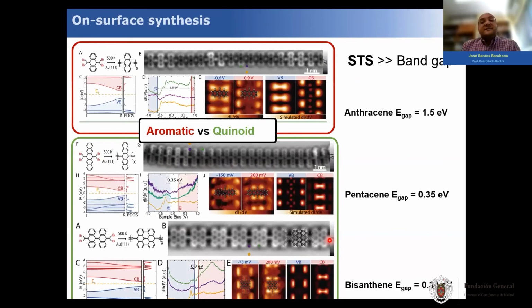Well, by STS, scanning tunneling spectroscopy, we can calculate, we don't calculate, we measure the band gap of the molecules. And for the case of the aromatic anthracene, this band gap is a low band gap of 1.5 electron volts. Whereas in the case of the quinoid structures, like the pentacene polymers and the bisanthene ones, we have these strikingly low band gaps of 0.35 electron volts and 0.30. This is striking because we can say that it's quasi-metallic.